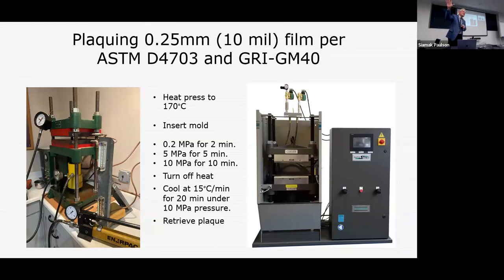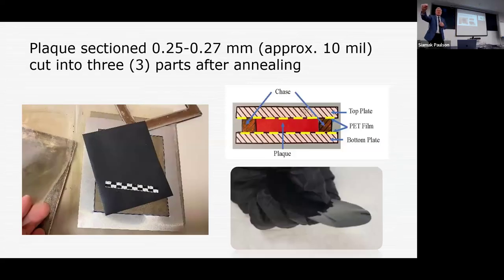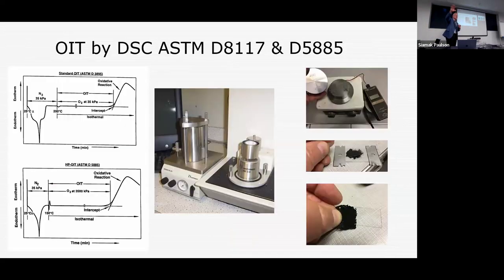And 42 does not stand alone. It takes 40 to make the plaque, and then 41 you'll hear about in just a minute. But this is GRI GM40, and this is making that 0.25 millimeter plaque. You're going to take that film that you made during this plaque, and then you're going to start by annealing this. You'll have to take the baseline OIT. And the OIT is not an or. It's an and. So you'll do standard OIT and high pressure OIT.